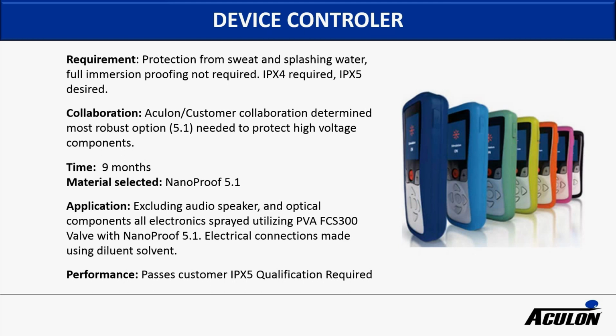Now there were some high voltage areas on these boards which determined that exposure to salt water through some of our more mid-level treatments still caused some failures. So we worked through a few iterative processes with this customer to identify these high voltage failure areas, determined that the most robust option, 5.1, needed to be utilized over the entire electronics of the board, including the electrical connections. So we developed a process with this customer to treat the entire board, treat specific sensitive areas, and then also utilize a process for making electrical connections with a diluent solvent when assembling the device. And we did achieve IPX5 on this device for that customer, and they see no failures in the field.